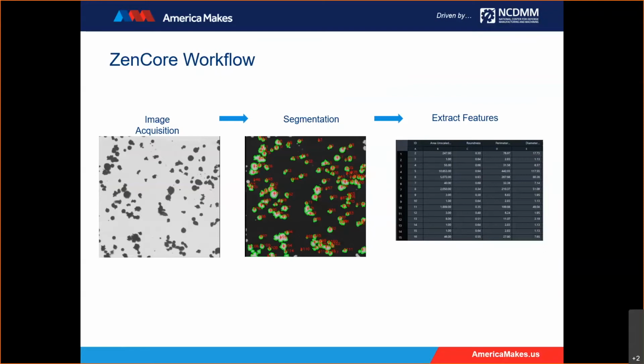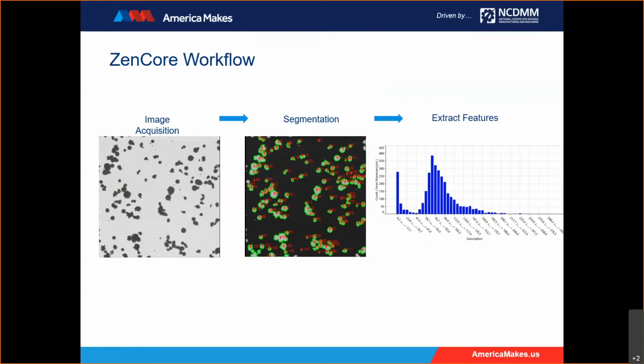When using a light microscope, we can acquire several tiles in both reflection or transmission mode. In both cases, the particles show up dark on a light background. Once we acquire an image, we can segment the particles from the background and label each particle with an ID. Then we can create a table with the particle features such as the area, the diameter, circularity, roughness, and the aspect ratio.